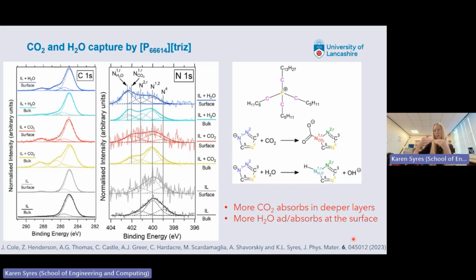And what we found was by doing a study where we changed the sensitivity of the measurements. So we had some very surface sensitive measurements, and then we probed a little bit deeper to look at a little bit more of the bulk compared to the surface layers of the material. And what we found is that the CO2 goes deeper into the ionic liquid, and so we actually find that there's more CO2 absorbing in the deeper layers. Whereas when we expose it just to water, we find that most of the water sits at the surface and it doesn't go into the ionic liquid very deeply. It kind of just sits there at the surface. So this is basically figuring out what is actually going on with how these ionic liquids react with the different gases. Effectively here, it's kind of separating them because the water sits at the surface and the CO2 goes deeper into the liquid.